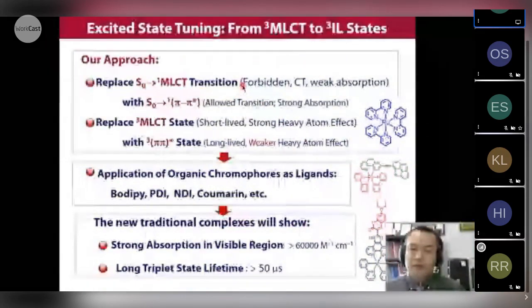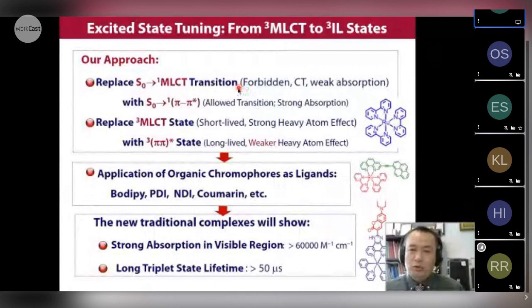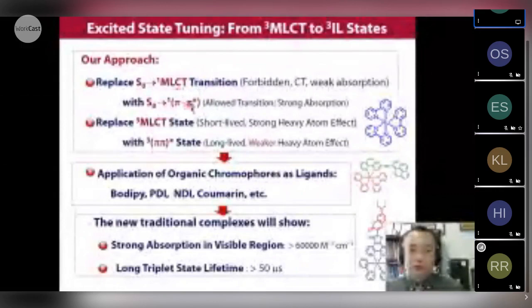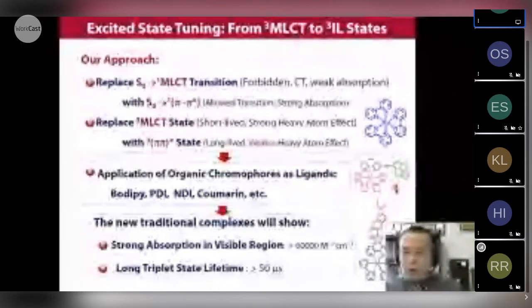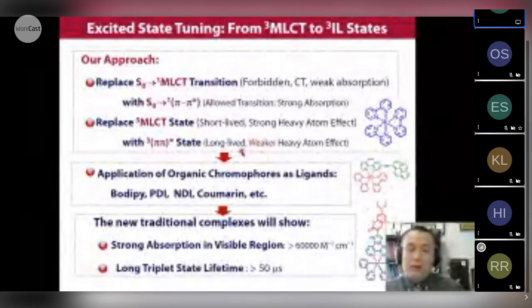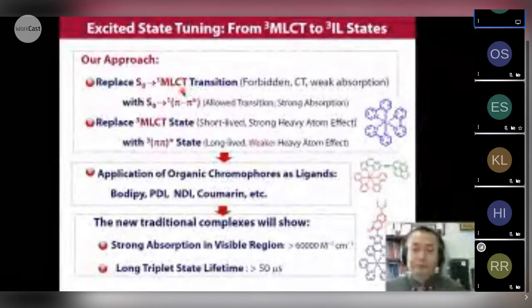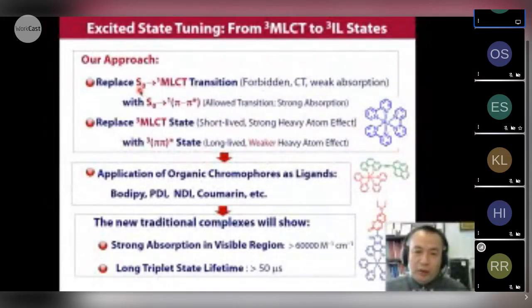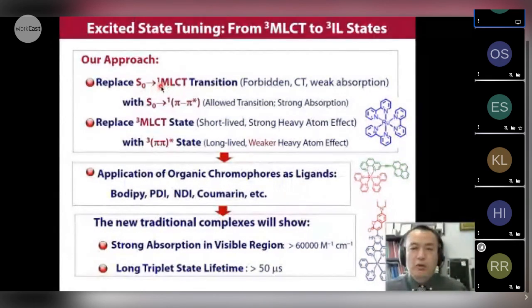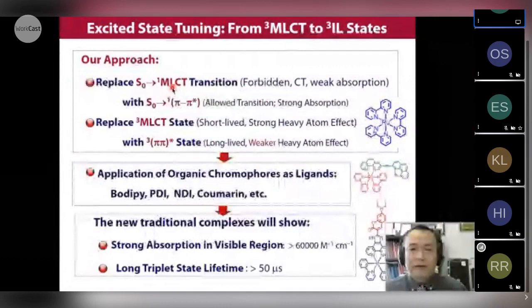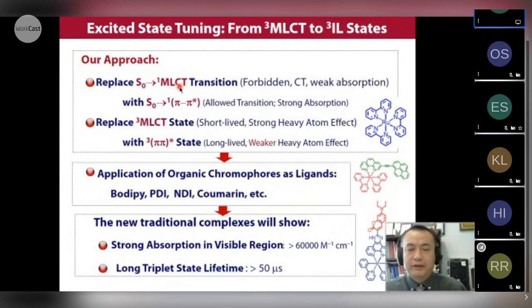Based on the research of other researchers and the work from my own group, we realized that we can change the normal MLCT state, that means the metal to ligand charge transfer state, to the π-π* state by introducing organic chromophore into the metal complex. We have to make sure the π-π* state is with lower energy than the MLCT state. We know the transition from ground state to MLCT state is actually partially forbidden because we have very poor molecular orbital overlap for the HOMO and LUMO. That will lead to a very weak absorption of light because the transition probability is low.